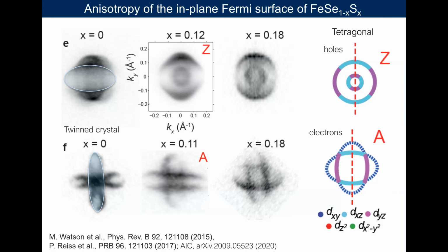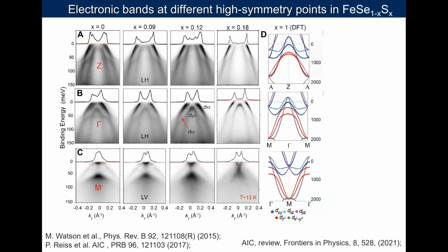The electron pockets usually have this two-ellipse, crossed-ellipse shape, and the spacing between these two crossed ellipses should be lifted by spin-orbit coupling, such that we have an inner and an outer hole pocket. And inside the nematic phase, they do become extremely elongated into peanut-like shapes. And these are the dispersions.